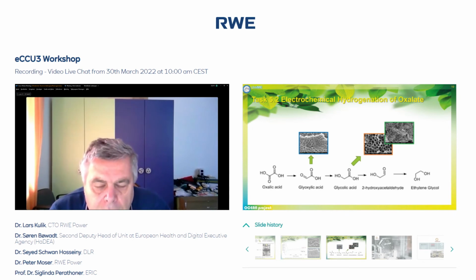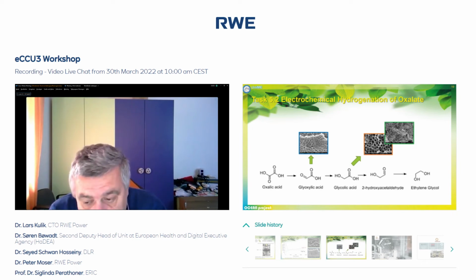So we have, of course, studied also the nature of the electroactive species, as I anticipated before. What we have identified is that the best system is a kind of small amorphous titanium oxide nanoparticles, which need to interact and be supported on these titanium nanotubes.